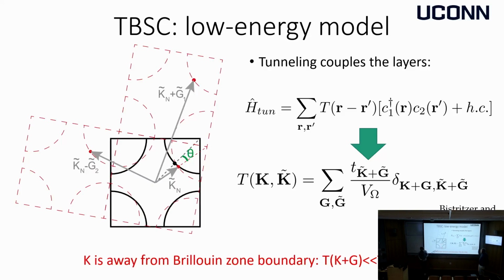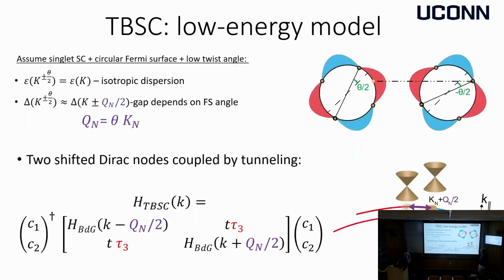There is a small parameter, so you can neglect those, and once you do that, you get a Hamiltonian that you can just solve. The qualitative difference, if you eliminate those higher terms, is that you don't get a flat band. That's the price you have to pay. Another interesting direction is to see whether you can engineer flat bands for superconducting quasiparticles. This model just gives you hybridizing Dirac cones, but they're continuum. There's no cutoff.